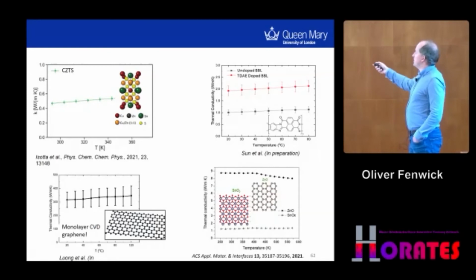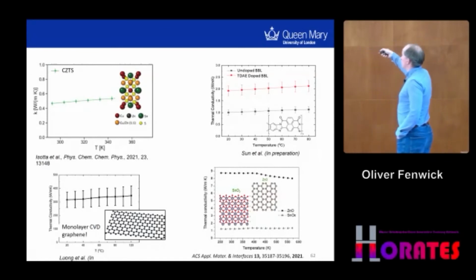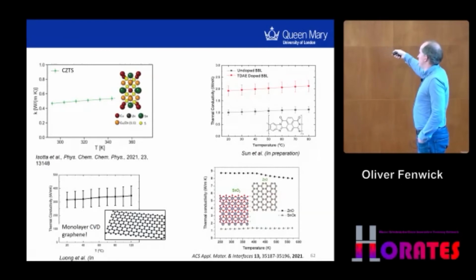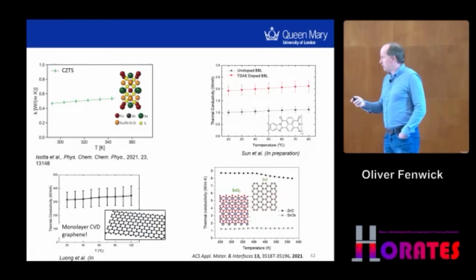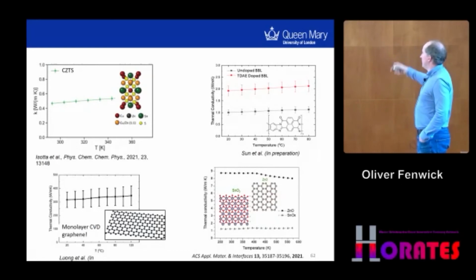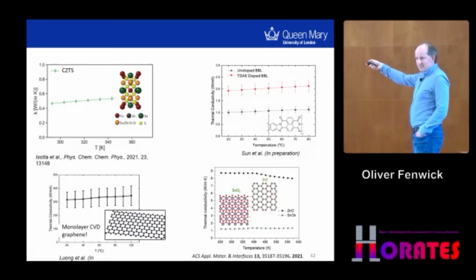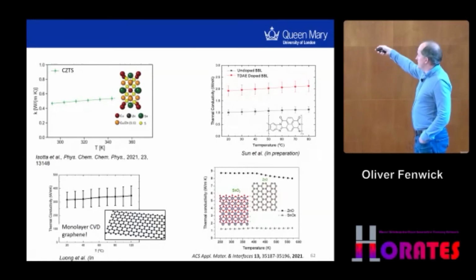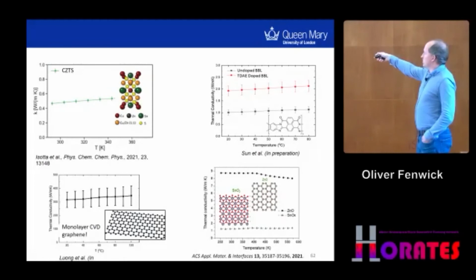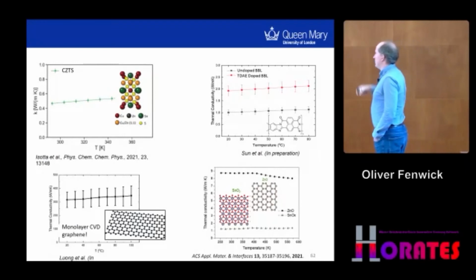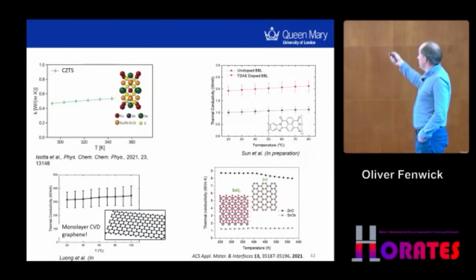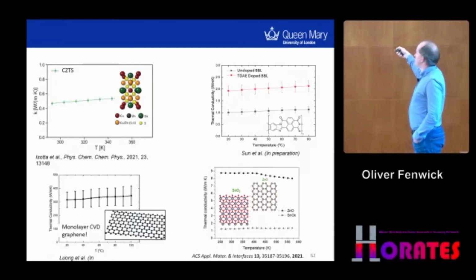So a kesterite thin film here, thermal conductivity 0.5 watts per meter Kelvin. Some metal oxides, tin oxides, zinc oxides. These values correspond with what you'll find in the literature for these materials. So I was again very happy with our system. Monolayer graphene, I was particularly proud of this. So this is CVD graphene, so we don't get the thousands of watts per meter Kelvin, but we get a value that's consistent with what's in the literature for CVD graphene, 300 watts per meter Kelvin or so. This polymer BBL, which comes from a node in this collaboration, has a high thermal conductivity, but that's understood.